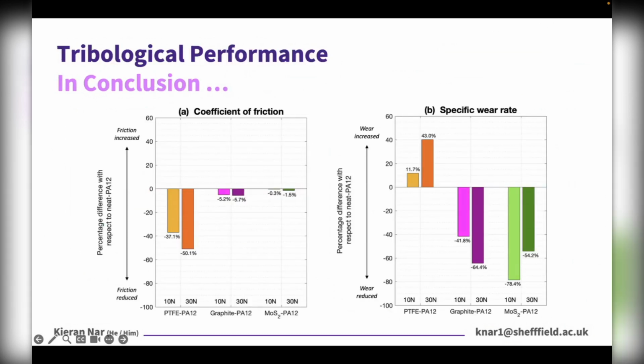So to put that into perspective for you, the addition of PTFE reduced friction by as much as 50%, but ultimately increased the amount of wear incurred during sliding, whereas the individual inclusions of graphite and molybdenum disulfide had no notable effects on friction, but did significantly improve wear resistance. And this was all relative to unfilled laser sintered nylon 12.